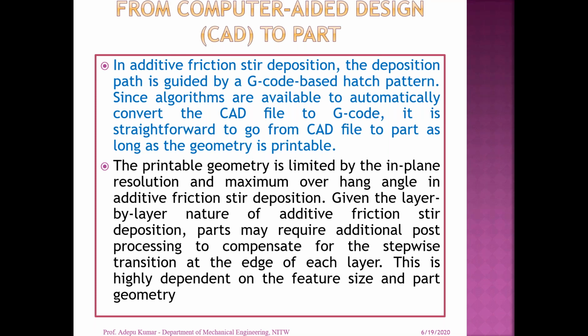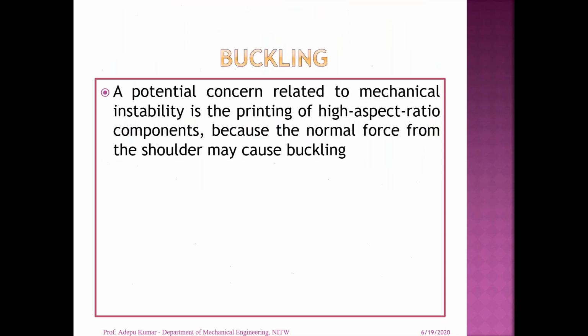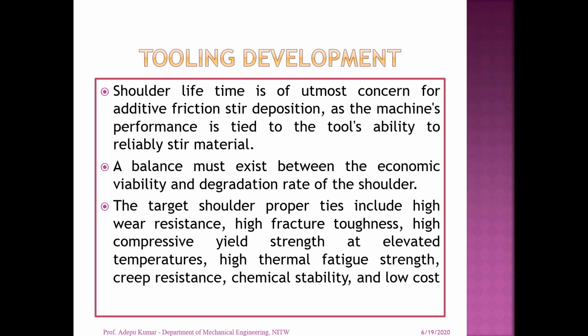The printable geometry is limited by the in-plane resolution and maximum overhang angle in additive friction deposition. Given the layer-by-layer nature of additive friction deposition, parts may require additional post-processing to compensate for the stepwise transition at the edge of each layer. Then another issue in friction stir deposition is buckling. When the height of the structure is very high, you need to apply vertical force. That vertical force is compulsory in friction stir additive or additive friction processes, so due to that, buckling takes place. That is another issue. Then tooling is also an issue because the tool is always in contact with the substrate surface. A lot of heat is generated, and that heat is transferred to the feed material, so it is always exposed to high temperature.